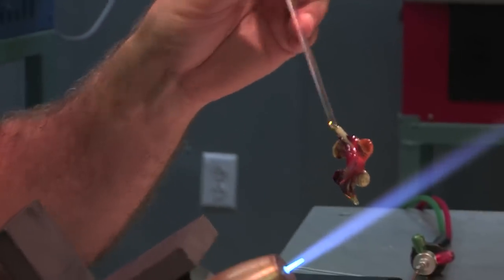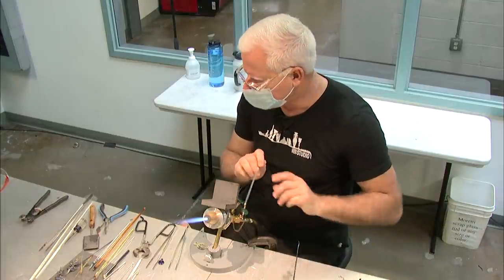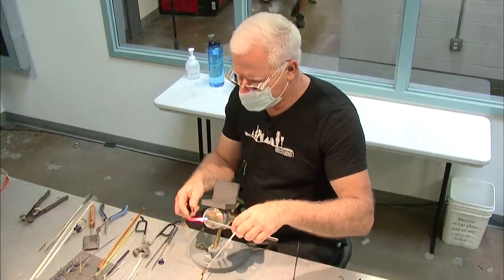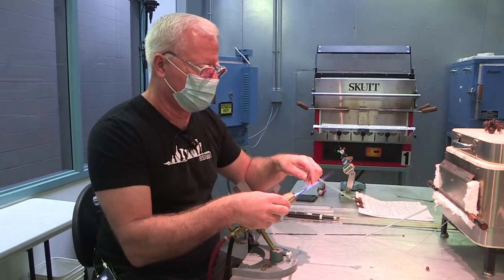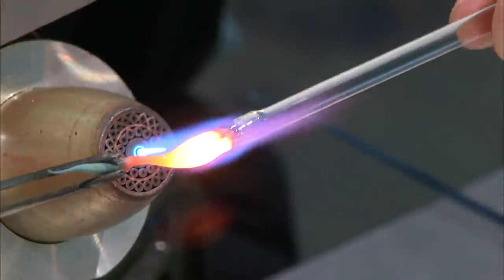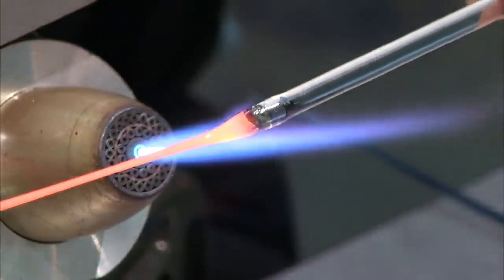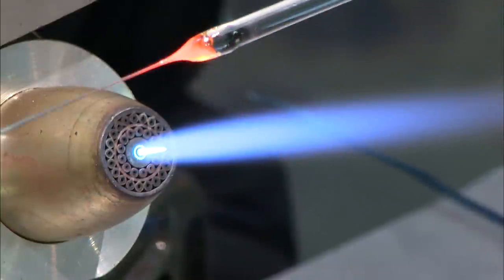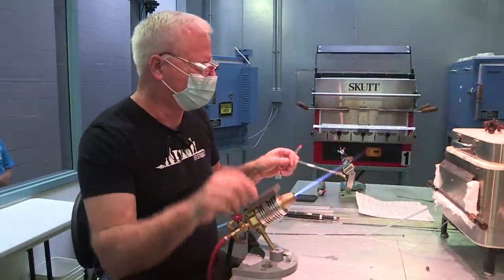All right. Previously, I have created some stringers out of my blue caramel. I can demonstrate really briefly how that happens. I know there are many techniques in which you can do this. Most people will tell you heat 2 inches at a time and pull. I need something that's really long, so I don't have a lot of time to just heat and reconnect. I just grab onto it, keeping it about maybe 2 inches from the base of the candle, and then just continually pull. And as long as you heat a center part, you can go and go and go and go, which is the way that I prefer, because it's going to be necessary for the next part.